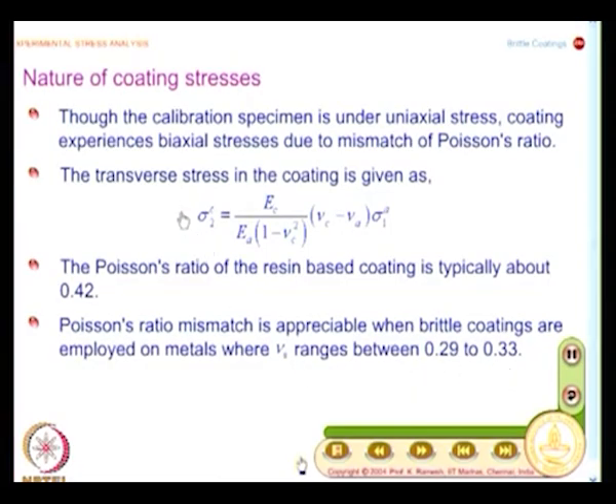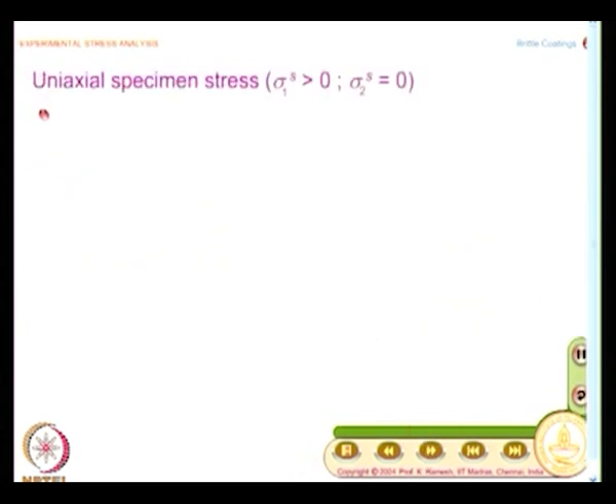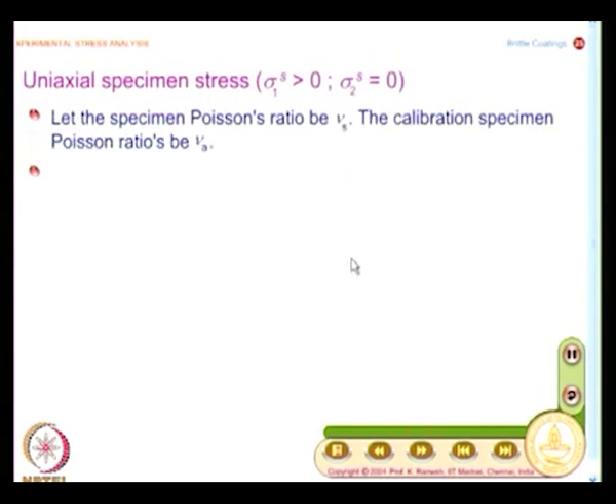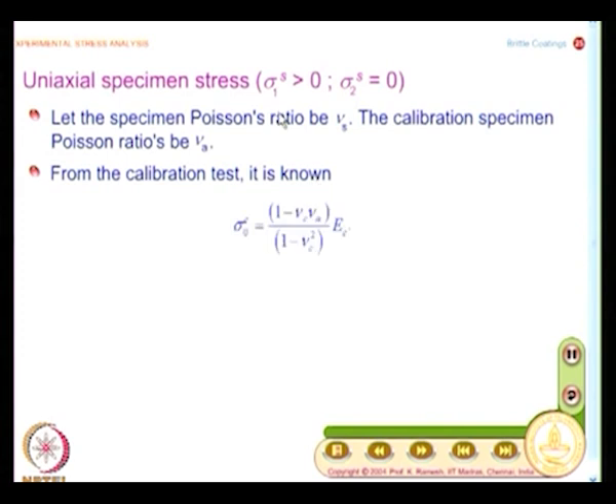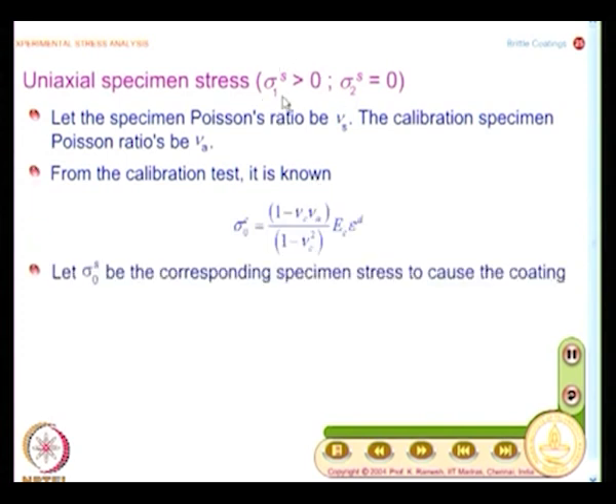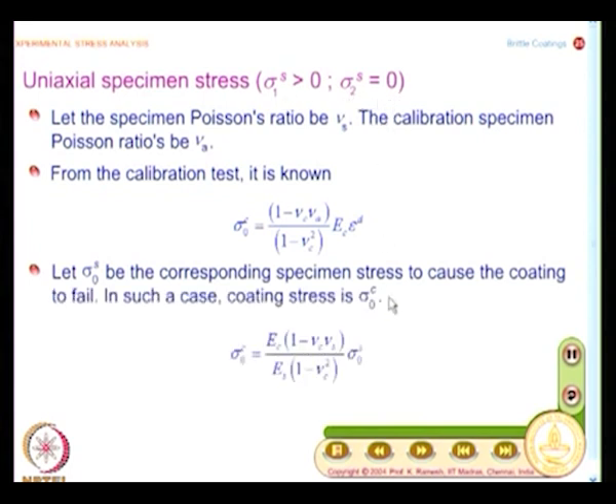Now, what we have emphasized is, for a uniaxial specimen stress, the coating experiences biaxial stresses. So, that is very important to keep in mind. Now, an actual prototype also fails with only one specimen stress acting on it, the other specimen stress is 0. Now, let us look at how the interpretation can be done. We have done a calibration test. From the calibration test, we have found out the failure stress of the coating, and that is written as 1 minus nu c nu a divided by 1 minus nu c squared, Young's modulus of the coating into failure strain epsilon d.